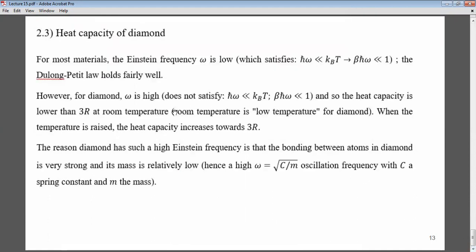Now, the heat capacity of diamond. For most materials, the Einstein frequency is low, which satisfies that beta h bar omega is much, much less than 1. And thus, the Dulong-Petit law holds fairly well. So the Dulong-Petit law holds, the Einstein model holds at high temperatures, where we found that it is constant. However, for diamond, omega is very high, which does not satisfy h bar omega much less than kBT, and so the heat capacity is lower than 3R at room temperature. Room temperature is very low for diamond. So when the temperature is raised, the heat capacity increases towards 3R.